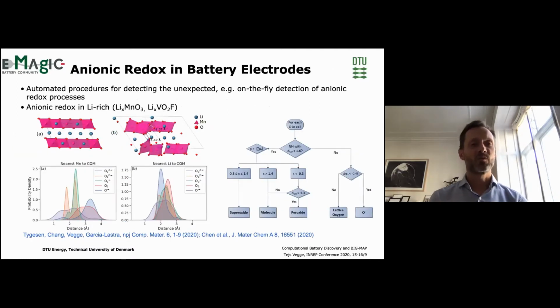Another important thing, which was also brought up by Professor Jean-Marie Tarascon yesterday, is also the search for, you can say, the unexpected. And this is a workflow for searching for anionic redox processes. This is work done by Tygesen and Juan Maria Garcia Lastra, where we use the computational workflow to identify oxygen pairs as a function of lithiation. This example is lithium-rich manganese oxide.